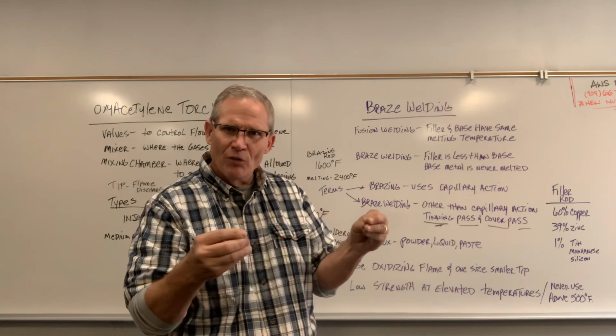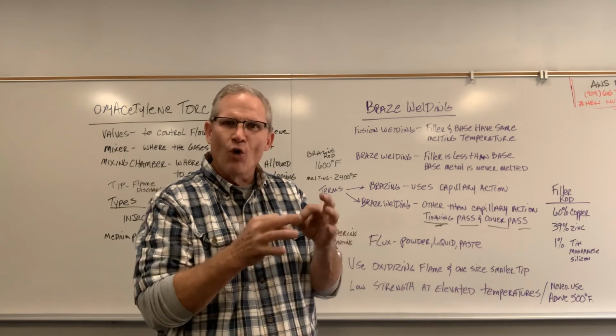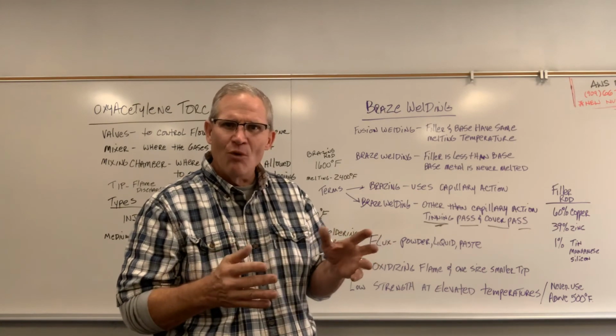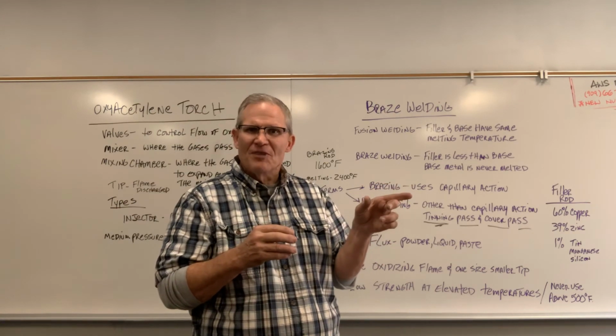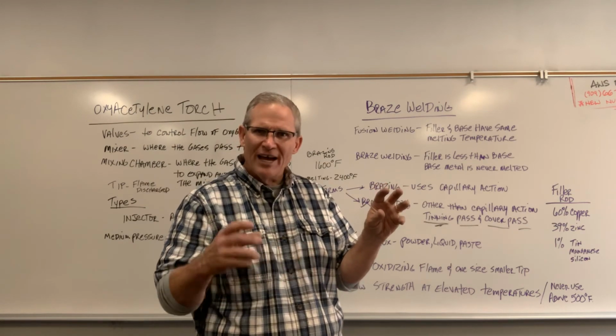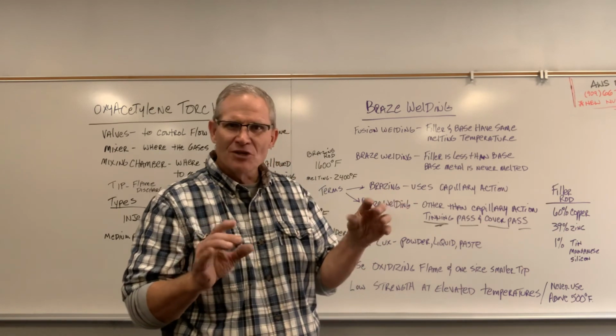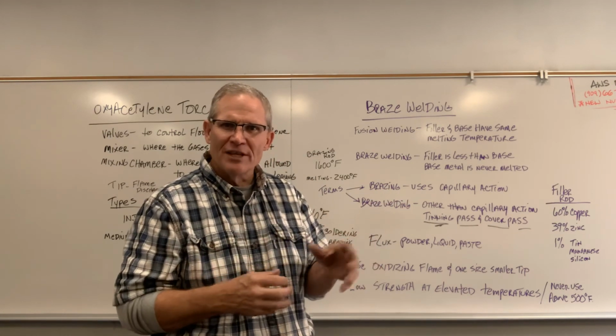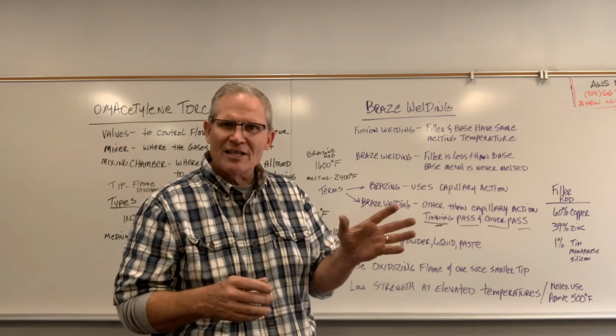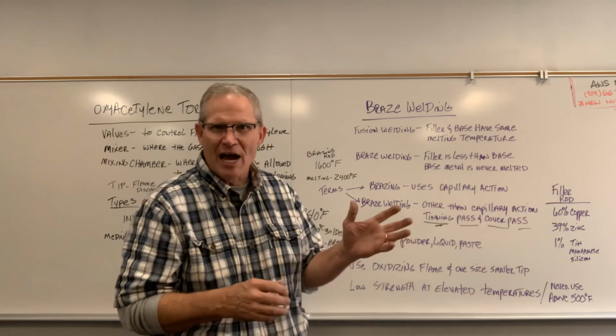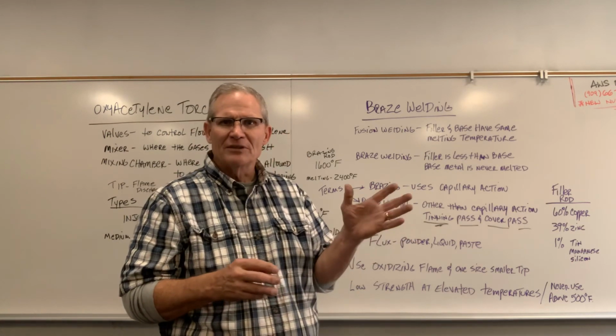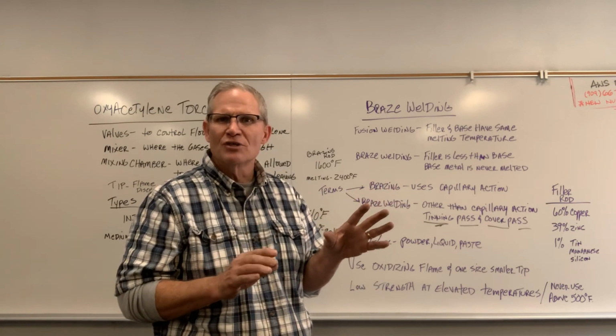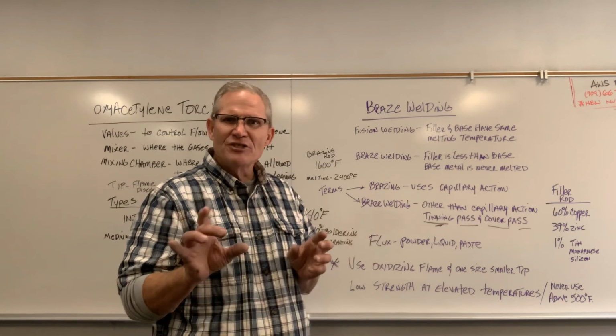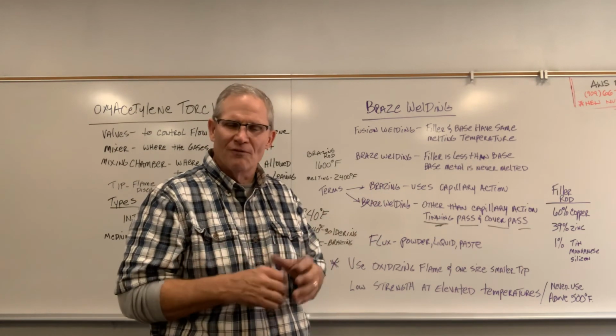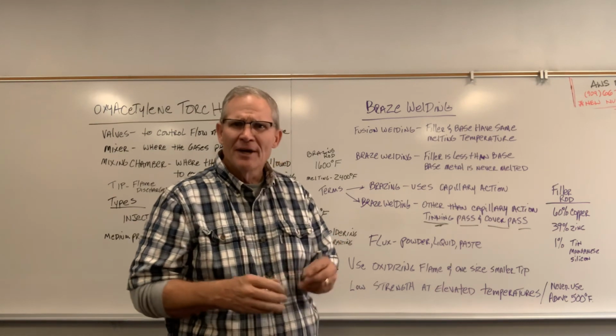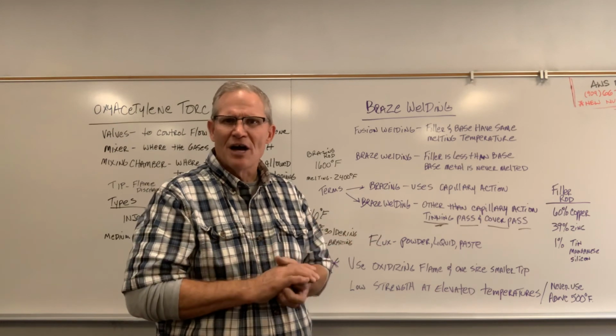When we cut the piece and pulled the coupling away from the copper pipe, we had voids all over in it. And what we found out was that the flux that was in the solder actually boiled against the paste flux that I was using. So they were working against each other and created all these bubbles in the solder finish itself. So we went and got solid 50-50 solder. Nowadays we use 90-10, with 10 antimony. But if you're ever going to solder, make sure you use a solid solder. And then just get a paste with a brush, and you can brush it onto your fittings and onto your pipe, and then start the soldering operation itself.